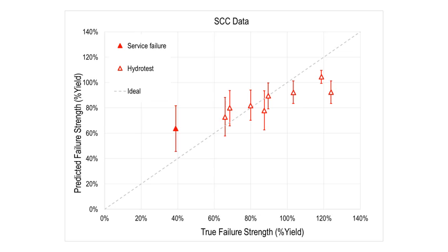Whereas if you're doing some hydro tests, like most of these data points are, either in the lab or in the field, all of the cracks in your pipeline are going to be, I'm going to assume, sort of randomly distributed between the correction factor of 0.42 and the correction factor of 0.84. You don't know where those cracks are in the crack and shed sequence, so it's reasonable to assume that they'd be fairly much scattered through there. So the way that these data points line up gives me a lot of confidence in the technique.